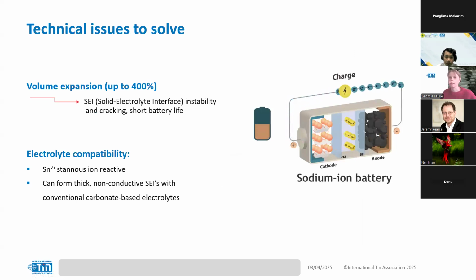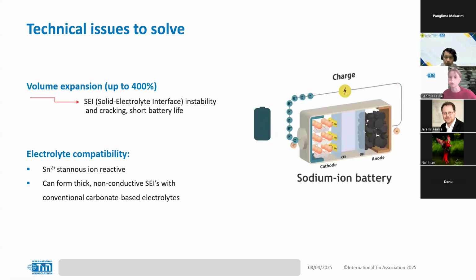One of the biggest issues of using tin is volume expansion. Tin can expand by over 400% during cycling, which can result in mechanical stress and poor conductivity or even cracking of the electrode. So if we look at this anode material here, if this was tin, for example, we could see in the diagram that it would be expanding and expanding and expanding. Eventually it can reach a point where it can crack, which can be detrimental for the battery and therefore can shorten the battery life.